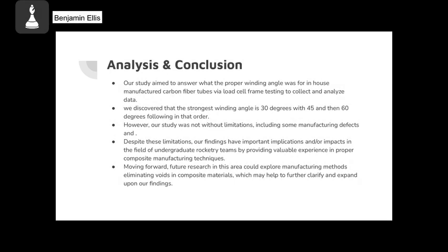So, the analysis and conclusions from our test. Our study aimed to answer what the proper winding pattern was for our carbon fiber tubing, specifically when it's in axial compression for the loading scenario. We discovered through our tests that a winding angle of 30 degrees is the strongest for withholding this type of load, followed by 45 degrees and then followed by 60 degrees in that order.